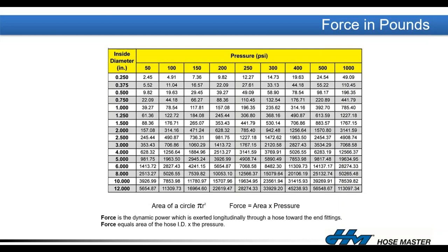So according to this chart, that 4-inch hose, when pressurized at 150 PSI, is actually exerting over 1,800 pounds of force on those welded connections in an attempt to try and elongate back into the tube it was formed from. That 1,800 pounds of force must be restrained by the cap weld and the fitting attachment welds, or else the hose is going to pull apart and it's going to fail catastrophically.